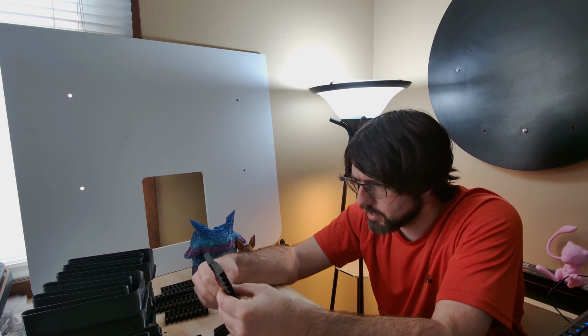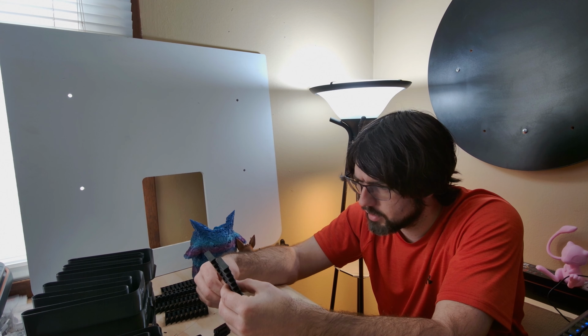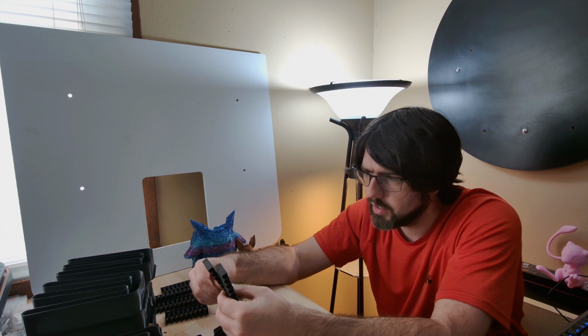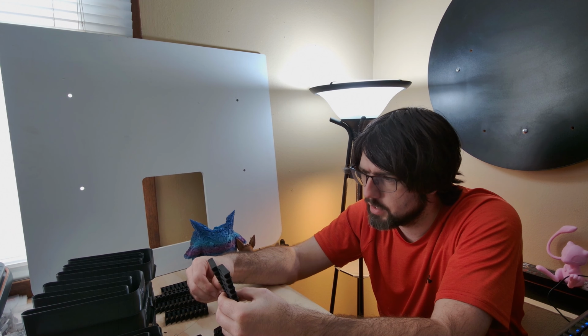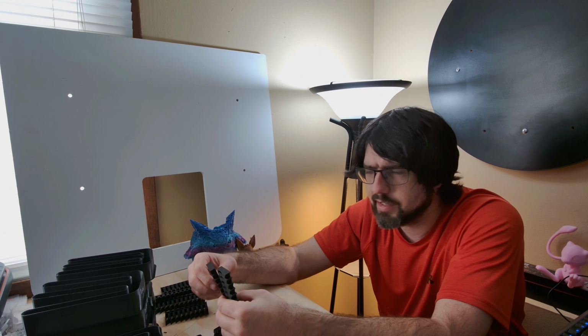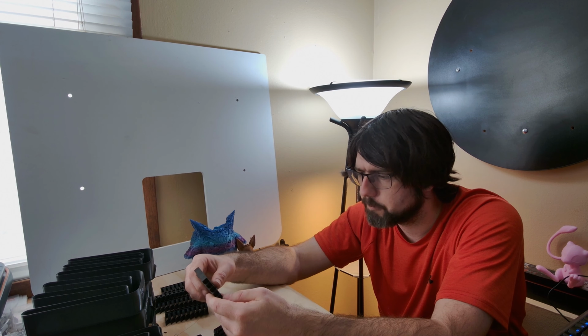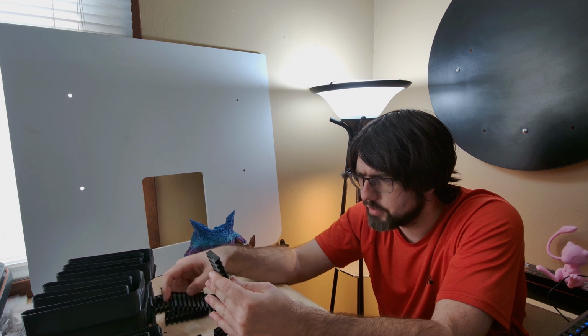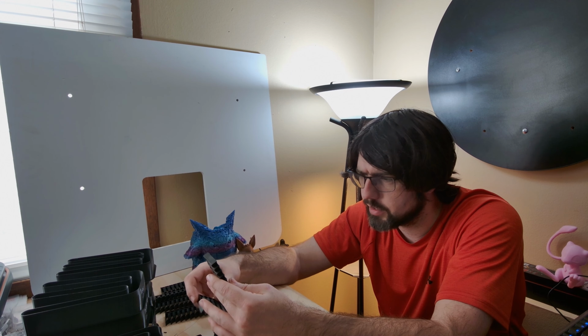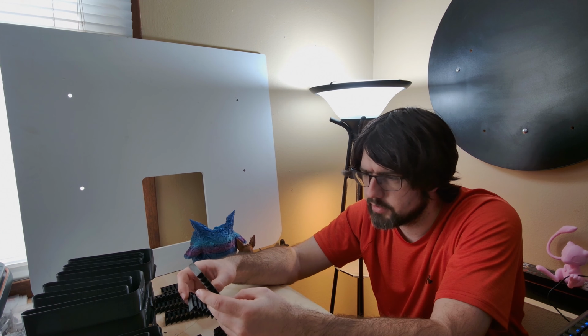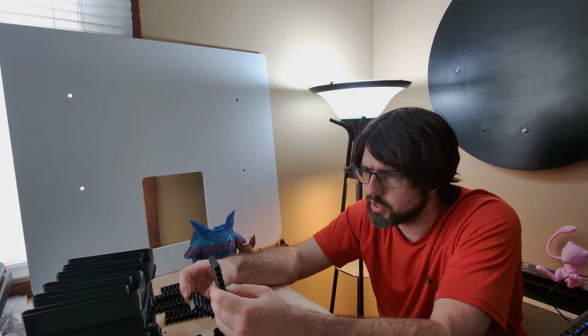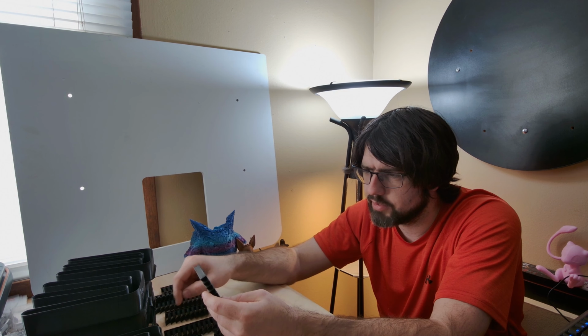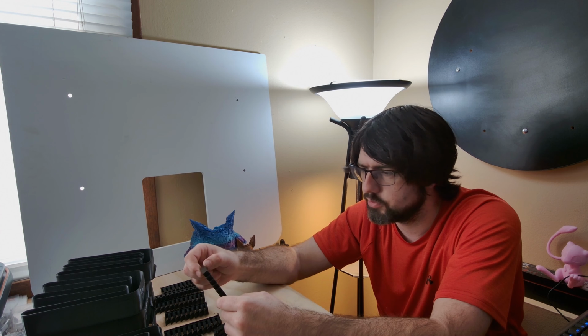Stringing. I had some light stringing around 230 to 215. Cleaned out really good around 210 up to about 195. And then oddly enough, I did get some stringing back in there. And as far as the Hyper, it stopped doing the stringing closer to 220. So only 230 and 235 really had stringing. And then it did finish out, and I didn't really have any of the stringing at lower temps than 220.